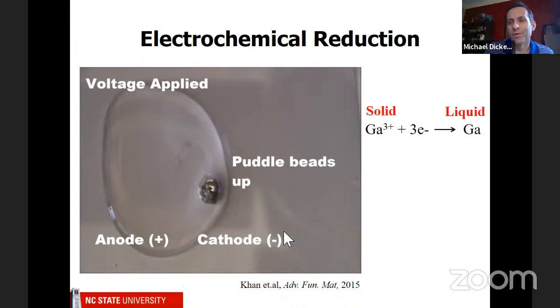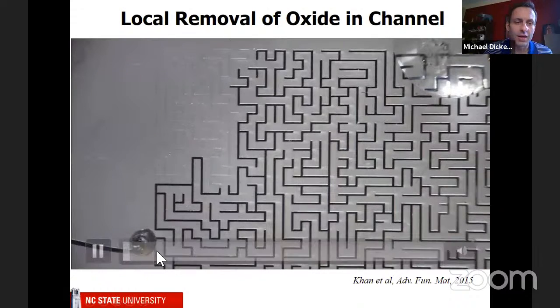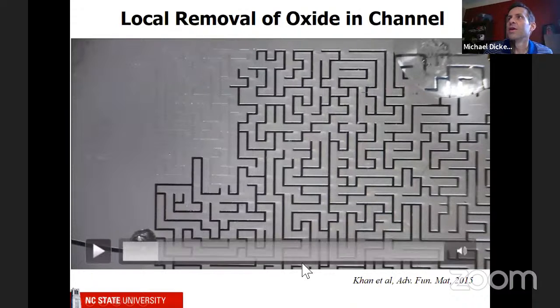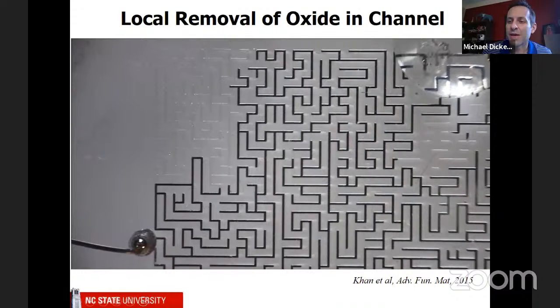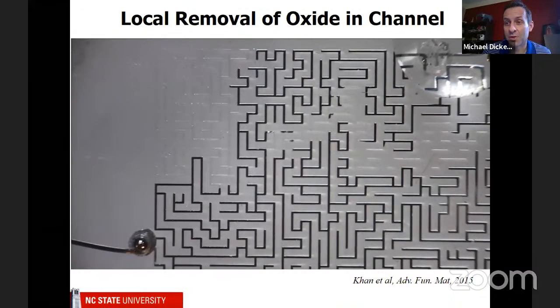Okay, so what is this good for? Well, just for fun, we made a maze, and I'm going to pause this also. We made a microfluidic channel maze. And there's an inlet, which is over here, and you can see that there's a droplet of water sitting on top of this. And then there's an outlet down here, which has a droplet of liquid metal. You can see that there's an electrode connected to the liquid metal, and there's an electrode, you can barely see it, but it's right here. So we're going to apply a voltage, and that voltage is going to remove the oxide from the liquid metal. And you'll see that this will solve the maze, because the solution to the maze is the electrical path.